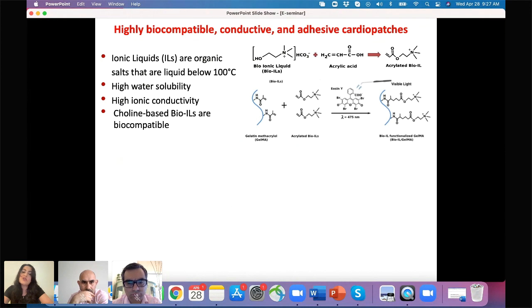But there are two limitations with these techniques. One is the level of conductivity that we achieve. It's usually less than the native tissue conductivity. And the second is, as we add more nanoparticles or conductive polymer in our hydrogel at higher concentration, they are not biocompatible and they can cause cytotoxicity.